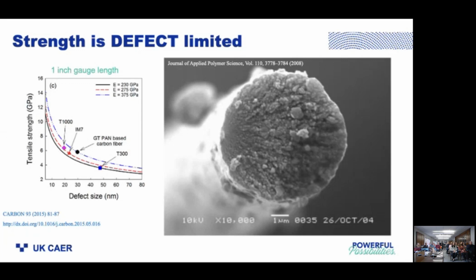A paper out of Georgia Tech described this pretty interestingly, plotting the tensile strengths of the filament versus the critical defect size on the filament. So if we take, for example, a fiber that has an average of 6 gigapascal tensile strength, that maps to a critical defect on the order of 20 nanometers, which is remarkable if you think about that. That means thousands of tons of these carbon fibers being produced cannot really claim that level of average tensile strength unless they have defects less than 20 nanometers over thousands of miles of carbon fiber.